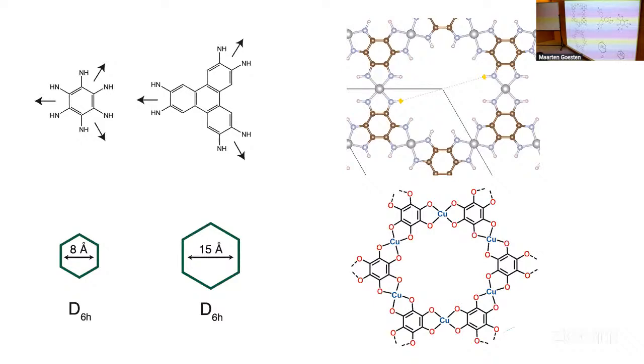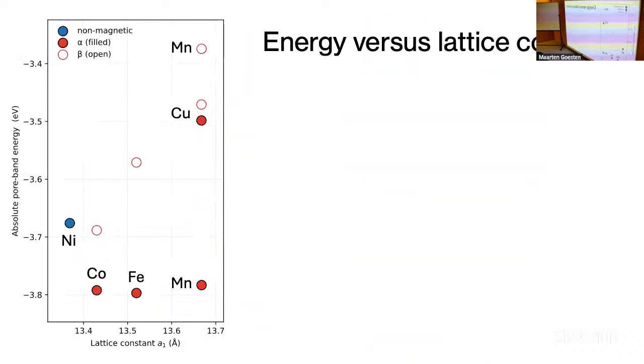So this pore space is too large. Even if we move to the oxygens here, there is again, probably at some higher energies, a pore band, but it's nowhere near as low as we find here, because here, with the nitrogen, we have an inner shell of hydrogens. You see that? So this pore is smaller than the pore here. So currently we don't find interesting pore bands for those systems.